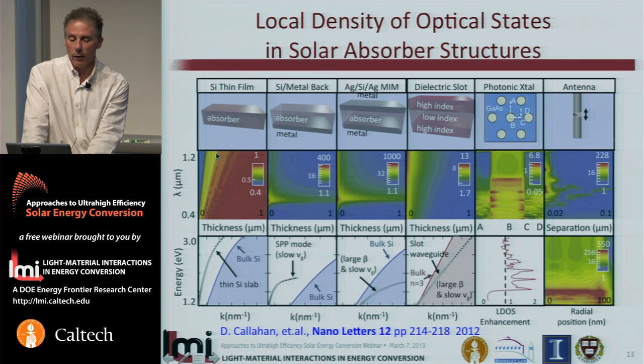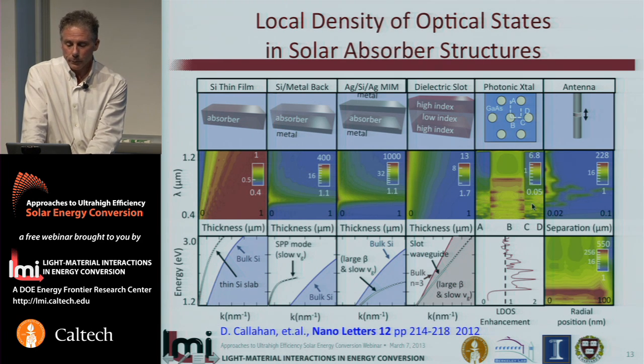That makes sense. It says that the number of modes that can be supported in a thin film is less than the number of modes in a bulk material. However, if we do something as simple as put a metallic back reflector, or make a dielectric slot structure with a high dielectric constant, low dielectric constant, high dielectric constant, or make a photonic crystal, all of these have the characteristics that for certain wavelength regimes and thicknesses, the photonic density of modes can be dramatically higher than it is in the bulk of that semiconductor material. So these offer opportunities for making wavelength scale structures that have more absorption per volume than their corresponding bulk materials.